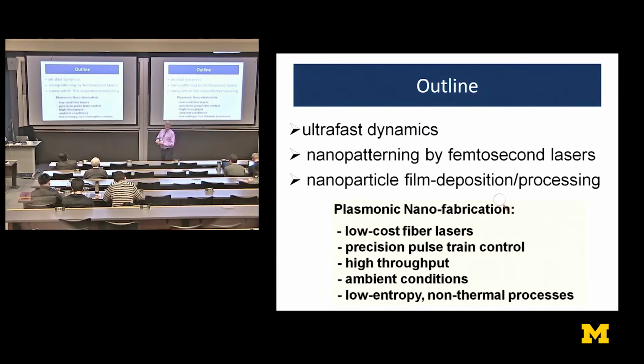These would be formed transiently within the time scale of the laser pulse itself. And since the pulse is very, very short, on a much faster time scale than thermal transport can occur, this is basically a non-thermal process. In other words, it doesn't involve melting the material or completely dissociating the molecules and atomic configurations, but modifies the potential without producing huge amounts of entropy.